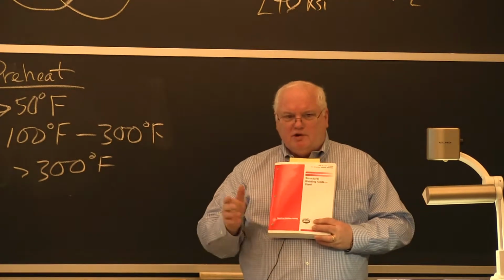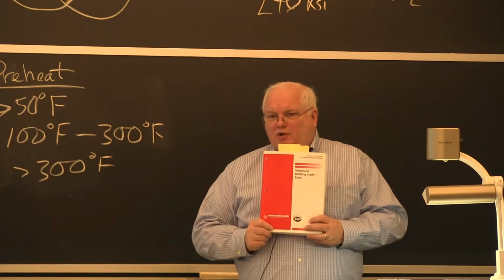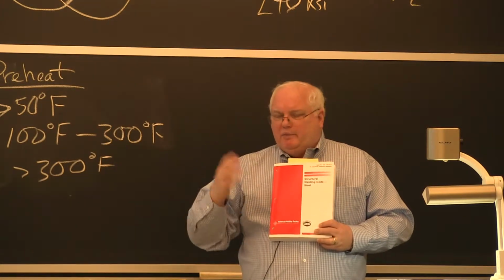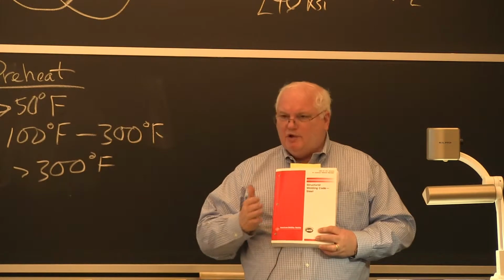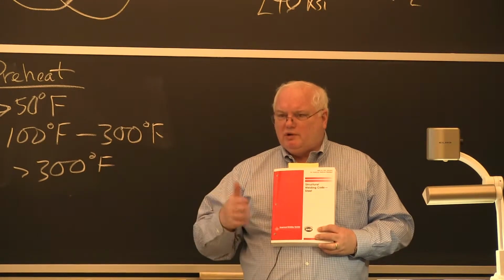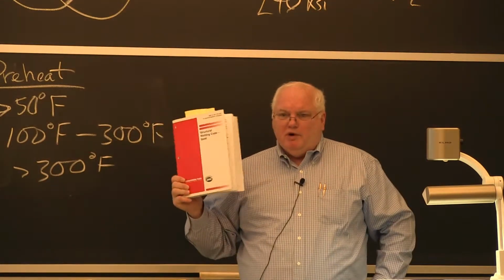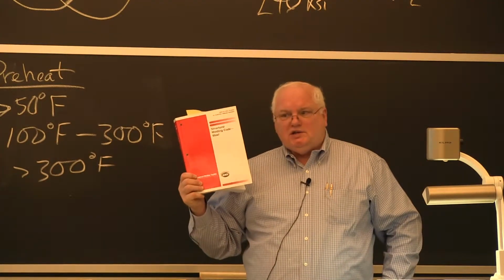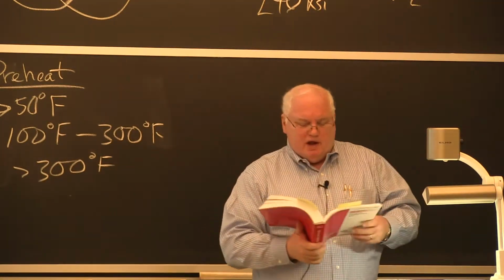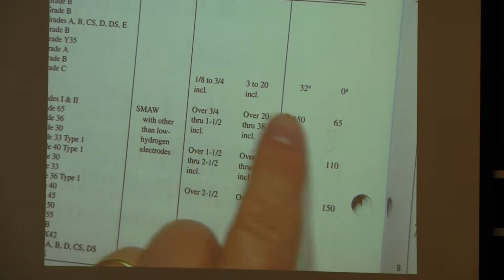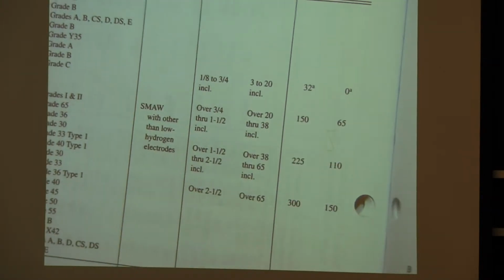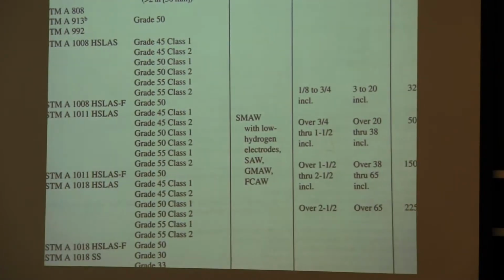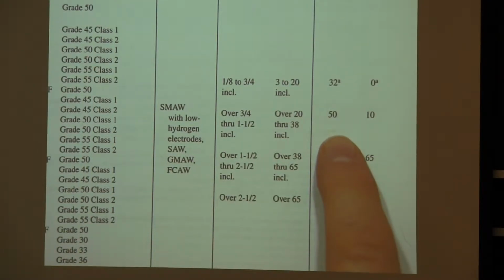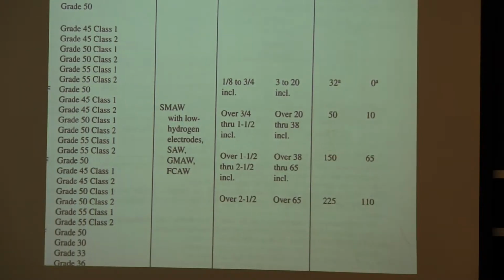ASME is American Society of Mechanical Engineers for all you MEs. And the boiler and pressure vessel code, and the structural welding code, which is basically the welding engineers or welding society, but civil engineers use it. Anybody building bridges and buildings uses this. Anybody building pressure vessels uses the ASME code. This says basically for less than 1/8 of an inch, you've got to be at 32 degrees Fahrenheit or 0 degrees centigrade. That's if you're 1/8 to 3/4 inch inclusive. Otherwise, for different steels, it might be 50 degrees or 100 degrees. Here's a steel over here, and it's going to be 32 or 50, depending on the thickness, okay?